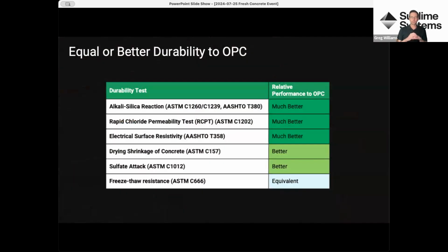Speaking of durability, we've conducted an extensive suite of durability tests. Our test suite is always growing as we learn about new tests that customers and partners care about. But we've gone through these with the initial version of Sublime Cement. These are mostly all of the key tests from ASTM, and also AASHTO, which is the equivalent of ASTM in the US for highways and infrastructure. They include tests for alkali silica reaction, or ASR, chloride permeability, sulfate attack, most of the main causes of degradation of concrete.